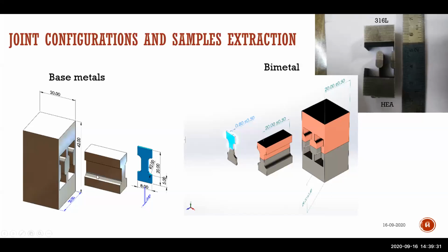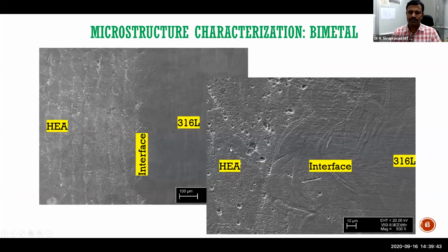Okay. So we have extracted again miniature tensile specimens from this and sliced a number of things. If it is a base metal like this, if it is a bimetal, two elemental systems will be like this, and we have extracted like this, and we have tested. Microstructure at the interface is not forming any undesirable phases or any serious precipitates, because when you have built 2 mm thickness, you have to empty the complete container and fill the other powder. By that time thorough cleaning precautions are to be maintained so that contamination will not be there.